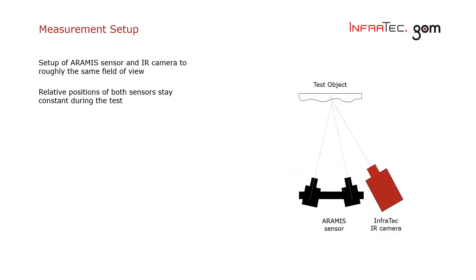The measurement setup itself, important here is to, of course, set up the ARAMIS sensor on the same field of view as the infrared camera. Another important aspect is that the relative positions of both sensors need to stay constant throughout the whole test. So therefore, there is no motion between the sensors allowed, as well as no motion relatively to the test part. Synchronization is another important topic, so there will be an electric trigger used between the Aramis system and the InfraTec IR camera. So every time the Aramis is taking a pair of images, the InfraTec camera is triggered externally from the Aramis system so that we can be sure that both measurements are taken at the same time so that they can be correlated later on time-based.